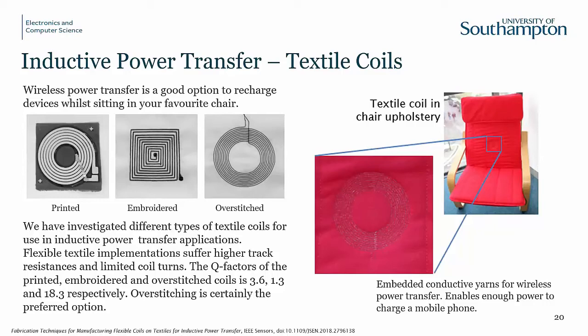With many embroidery machines, you have two thread paths, and you can put a conductive standard multi-wire Litz wire in the bottom conductive thread path and overstitch with the other thread path. So the machine will very quickly make this coil pattern for you. We've compared the various parameters of these coils, and this overstitch approach is the best. We've put this onto, for example, a chair, so this might be your favourite chair at home, and if you sit down there and you've got a corresponding coil on your clothing, you can certainly charge your mobile phone, so we demonstrated that.